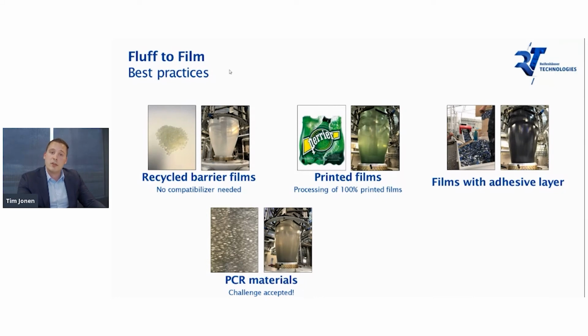He sent over this material and said, okay, if I try to process these materials on my conventional blown film line, I end up with huge holes in the film, and I wasn't even able to produce any film out of it. So we gave it a shot and tried to run the material through our Fluff to Film line. And thanks to the better homogenization as well as the venting units in the twin screw extruder, we were able to make a very decent film out of it.